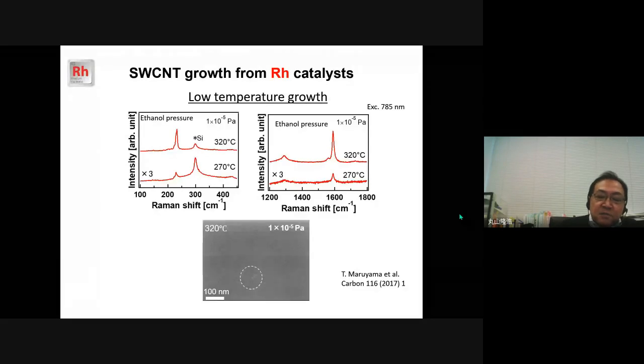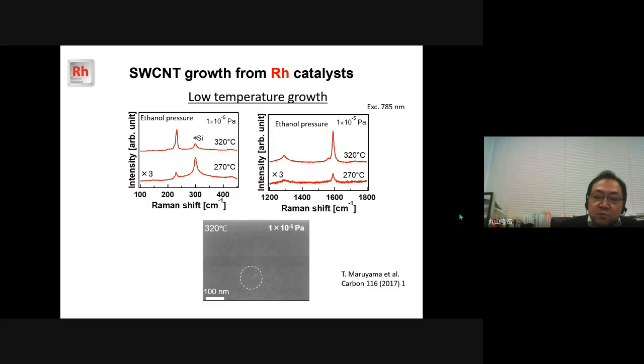This shows the Raman spectra for SWCNTs grown from rhodium catalysts at low temperature under the optimal ethanol pressures. Both RBM and G-band peaks were still observed, even at 320 and 270 degrees C. That is, single wall carbon nanotubes grew below 400 degrees C.